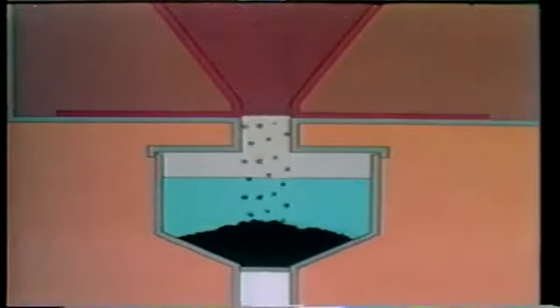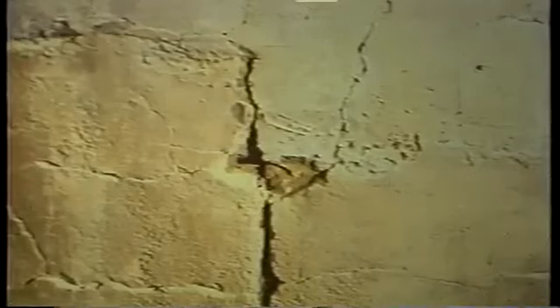The bottom ash hopper can have refractory problems caused by the bottom ash that collects there. The ash is very hot when it enters the hopper. Normally, it is cooled quickly by water in the hopper. However, this water must be drained every once in a while to get rid of the accumulated ash. While the hopper is empty, hot ash can heat the refractory on the inside of the hopper. This problem is made worse by the sudden temperature change that occurs when the ash hopper is refilled with water. The combination of heating and then sudden cooling of the ash hopper can lead to spalling and cracking of the refractory.